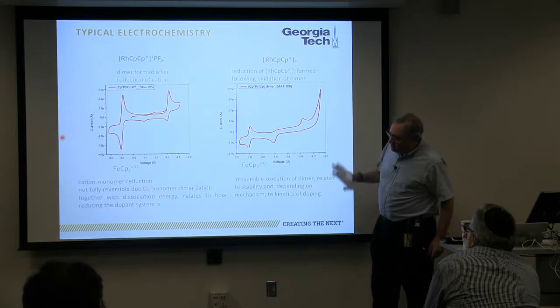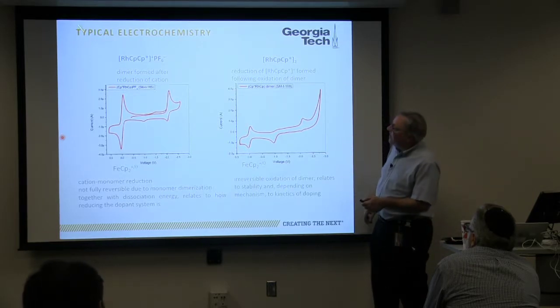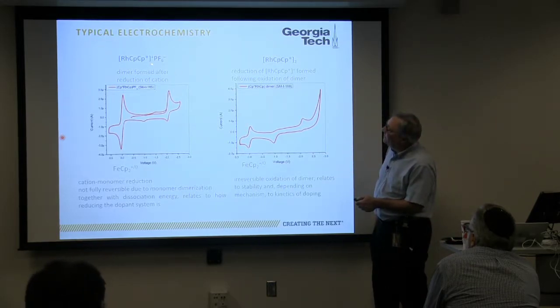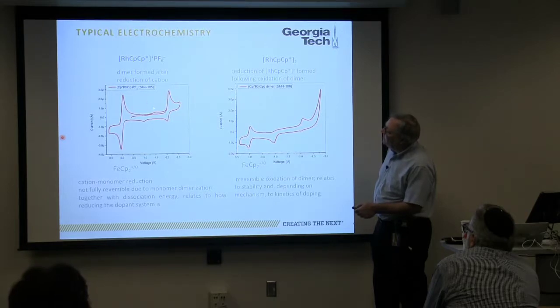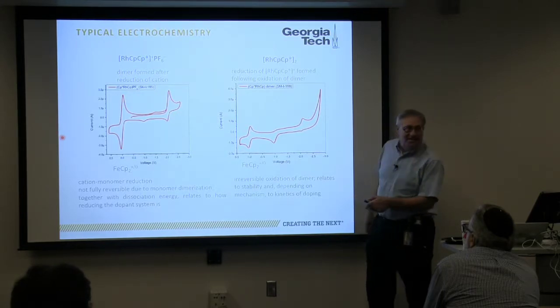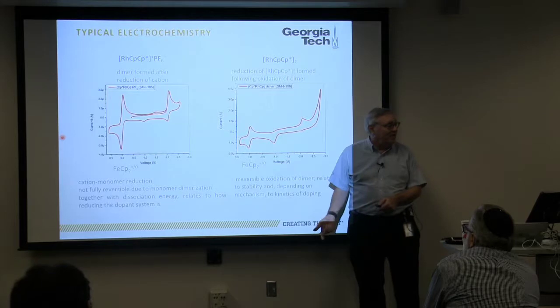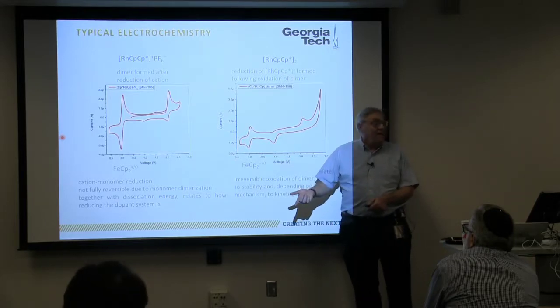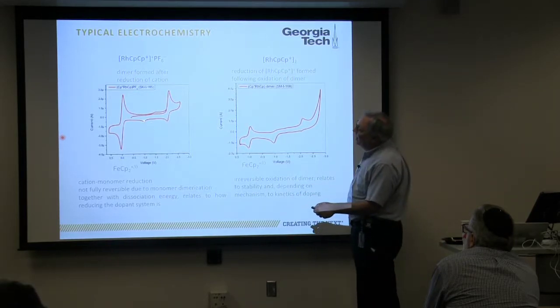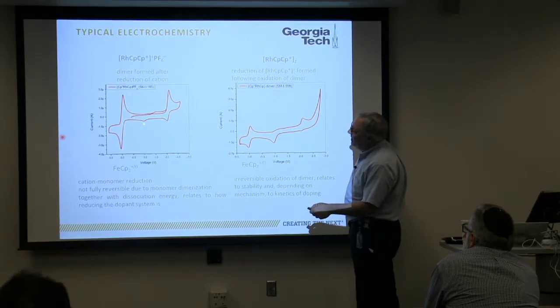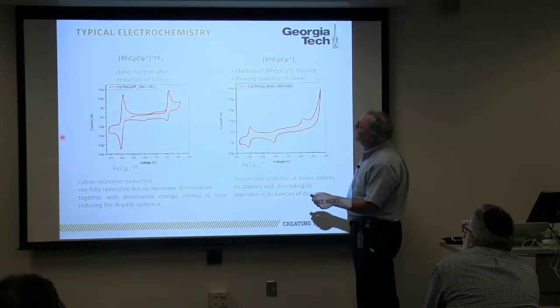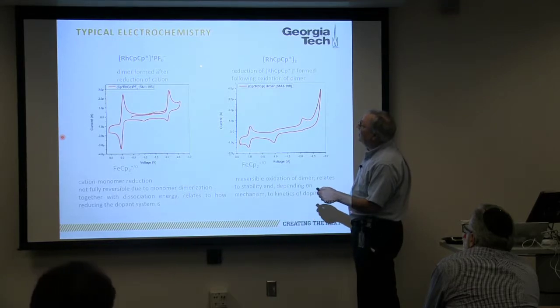And that was not surprising: if you take a cation of a rhodium compound and you reduce it, and then you look in an electrochemical cell at the reverse wave, you can see there's more current here than there is there. Which means that when we reduce this to the 19 electron compound, it's actually going away before we can reoxidize it. And then when we look back, we can see there's a blip over here, and that blip is due to the dimer of that compound.